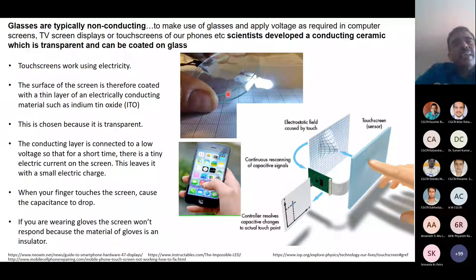So what the scientists discovered over a period of time, which is visible in this picture, is that they developed a coating which is called indium tin oxide. It's again a ceramic, remember, an oxide. So if you coat a thin layer of indium tin oxide on glass, then that part becomes conducting. Indium tin oxide gives the conductivity. So in this picture, for example, the inside surfaces of this glass are coated with ITO, but because it's transparent, you can't really distinguish. On this side, the supply is there, and on this side, they held an LED in between the two surfaces, and they are showing that without any wire through it, it's lighted up. That means this glass is conducting, and that's because of this transparent oxide. So this is an amazing material, and it's there in so many of the devices that we use, without which these devices will not work, right?